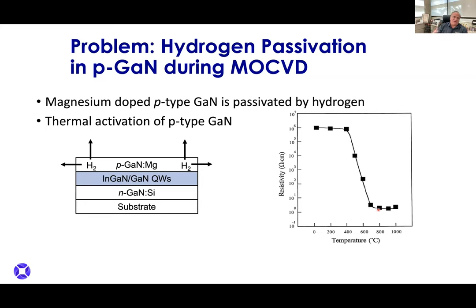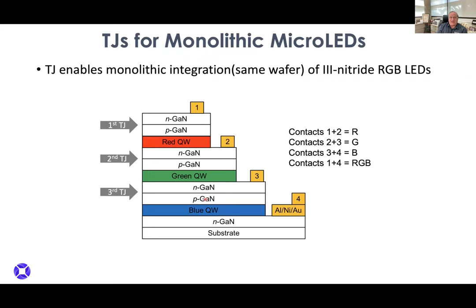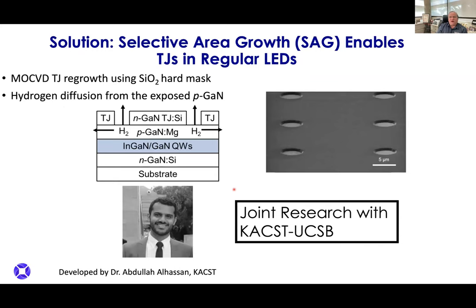But when we tried to do this in micro-LEDs, we found out that with this P-type gallium nitride, the hydrogen was being blocked by the N-type. And so one of our researchers at the time, in joint research with KACST, Dr. Abdullah Alhassan, said, well, let's just put a little hole here to let the hydrogen come out in our micro-LEDs, and that will let the hydrogen diffuse out. And so indeed, this is what the top N-type gallium nitride tunnel junction looks like. That solved how to make a tunnel junction work in the LED space.